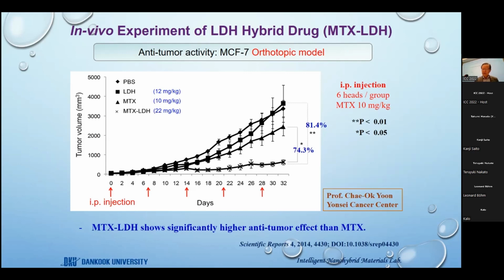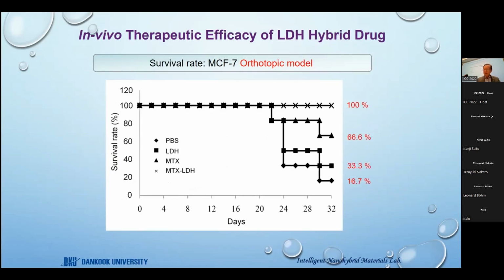Here you can see the in vivo toxicity. The survival rate of MTX LDH is determined to be 100% compared to the control. Why? This result suggests that our clay drug significantly enhanced the therapeutic effect and, as a consequence, increased the survival rate compared to the free MTX, which is well consistent with the results of a biodistribution study, which will be discussed afterwards.